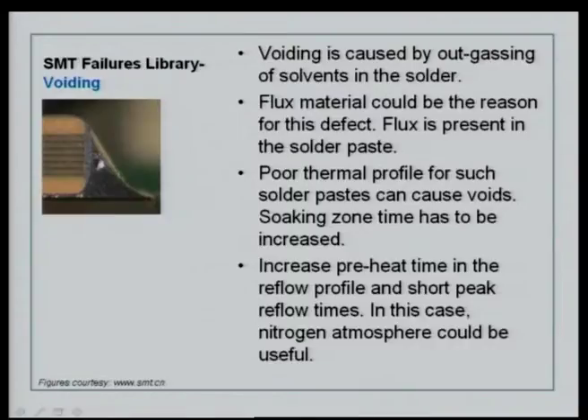The other defect is voiding. Voiding, you can see here, this is a void in a very good, otherwise very good solder joint. Voiding is caused by outgassing of solvents in the solder. So, typically you can assume that this is a very good joint formed, but unfortunately there is a defect which has been caused by outgassing of the solvent in the solder paste material, and that has created a void. Flux material could be the reason for this defect. Flux is present in the solder paste, as you know, and poor thermal profiling for such solder paste can cause voids.